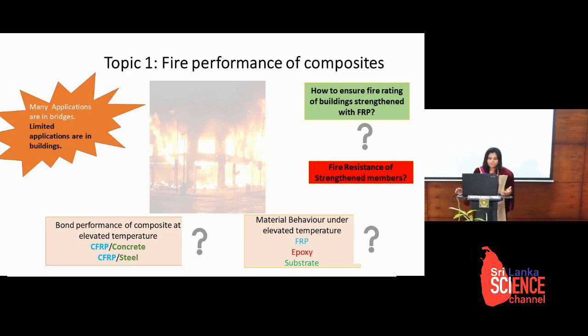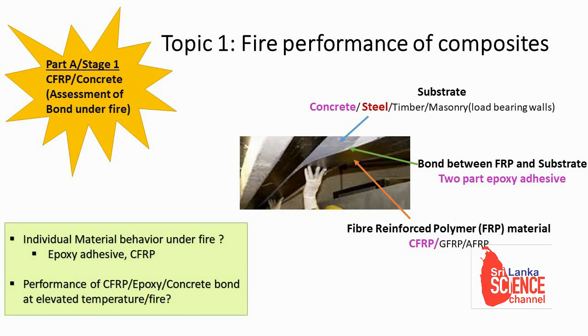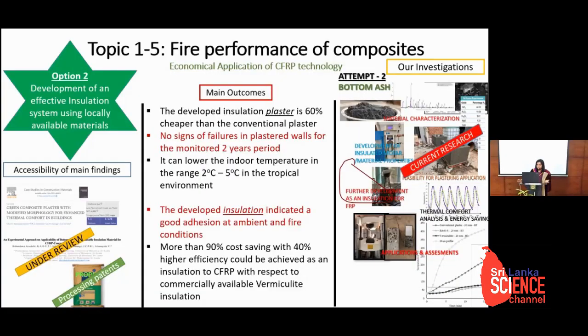If you see, the composite actually has three elements. All three elements should work properly to have a composite action, that means for effective load transfer. So the substrate may be concrete, steel, timber, or masonry. And then the fiber reinforced polymer material, either CFRP, GFRP, or AFRP. And the bond between these two materials. So that means if you want to assess the performance under fire, we have to know the individual performance as well as the composite. So the first step, we approached plaster development.